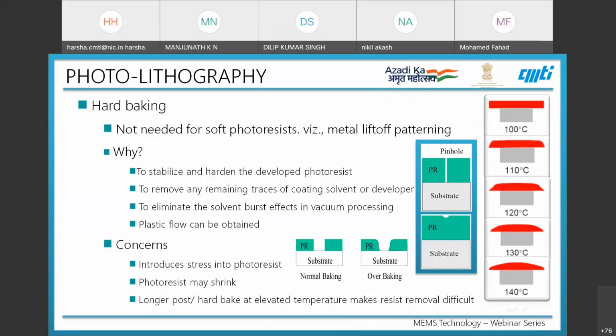After the development, there is a hard baking process. This may not be required for soft photoresist, such as metal lift-off patterning. But the necessity of hard baking is to stabilize and harden the developed photoresist and to remove any remaining traces of coating, either solvent or developer, present on the wafer.